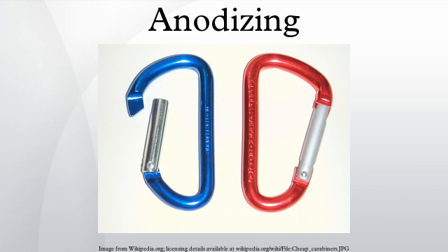susceptible. Although anodizing produces a very regular and uniform coating, microscopic fissures in the coating can lead to corrosion. Further, the coating is susceptible to chemical dissolution in the presence of high and low pH chemistry, which results in stripping the coating and corrosion of the substrate. To combat this, various techniques have been developed either to reduce the number of fissures or to insert more chemically stable compounds into the oxide, or both.